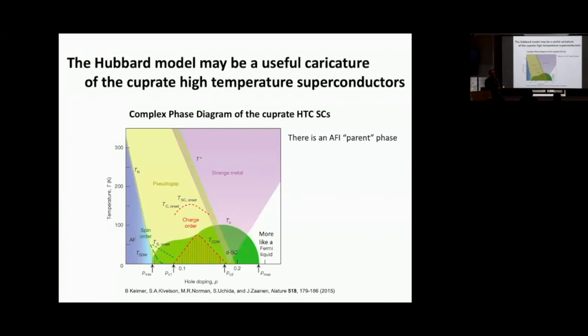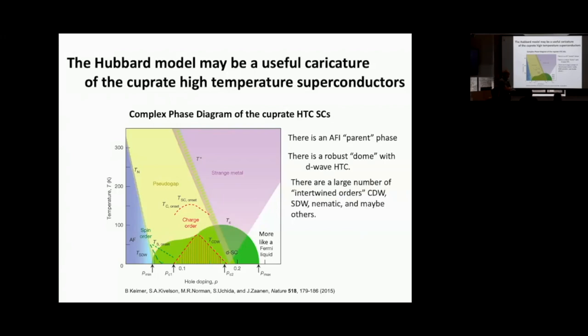What are some of the salient things that one would like to understand that this phase diagram presents us with? Well, one is there's the antiferromagnetic insulating parent phase. There's a robust dome of d-wave superconductivity with high transition temperatures. There's a large number of other ordered phases that have similar energy and temperature scales as the superconductivity itself. This is something we've referred to as intertwined orders.